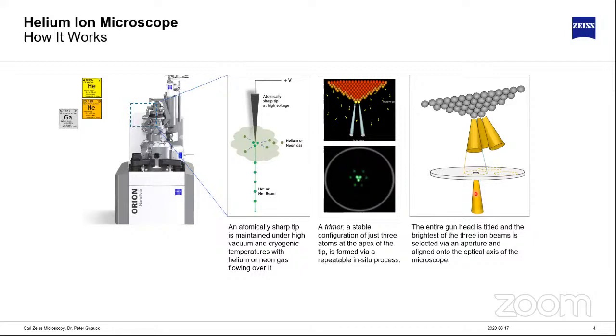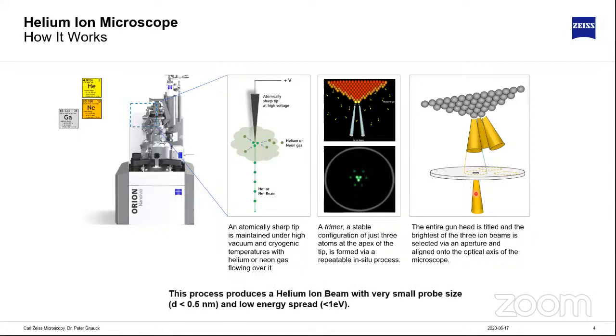And that actually results in the fact that we can focus this beam into much smaller spots than an electron beam. The other thing which is beneficial for that is helium ions have a higher mass than electrons. That means the wavelength is shorter, and that means we're not diffraction limited like we are in an electron microscope. And therefore, we can actually focus the beam in smaller spots, definitely clearly below 0.5 nanometers, and we can do excellent high resolution imaging with that.